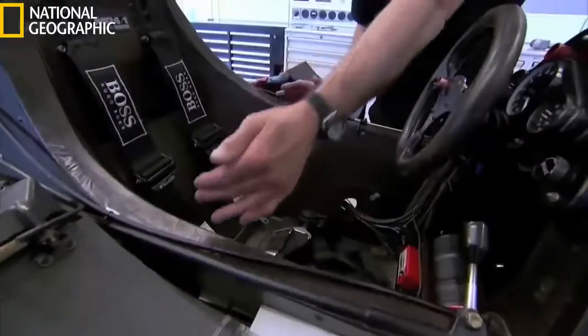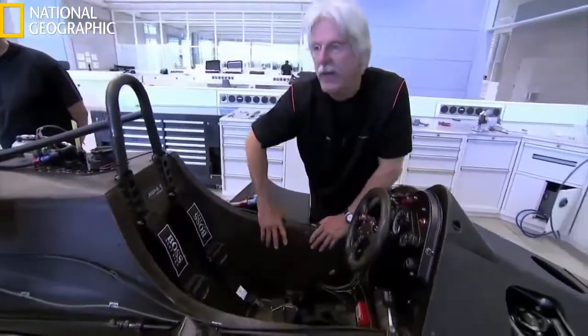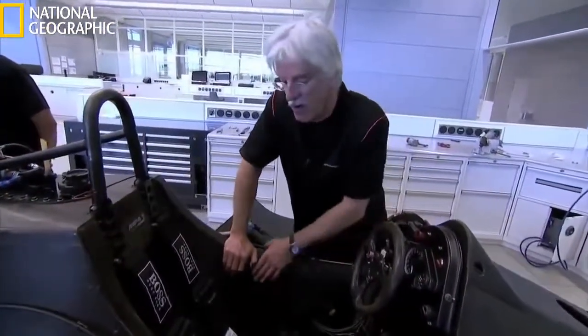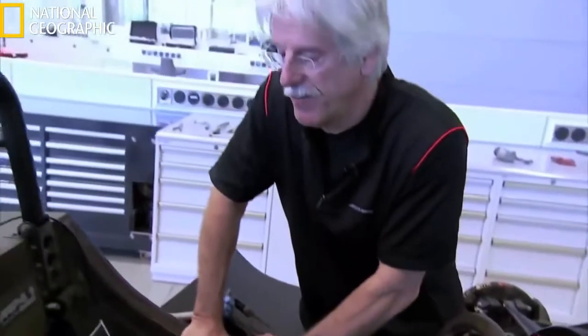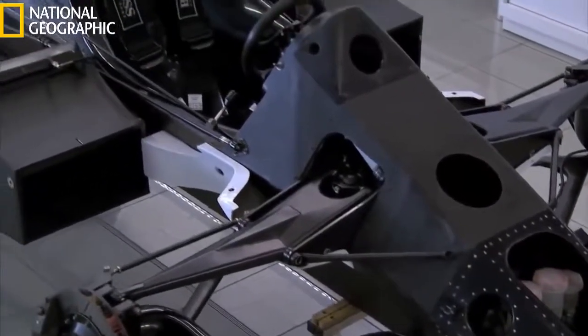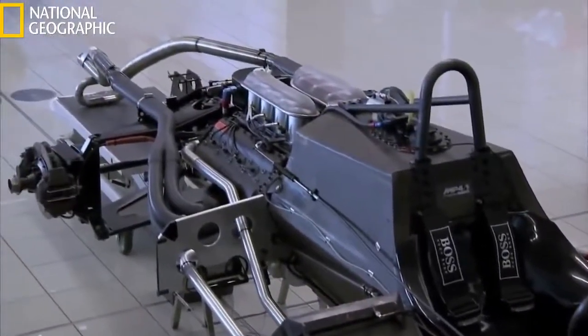Everyone had narrow chassis, same kind of shape as this. But because of this inherently weak area here, the aluminium chassis were twisting. When we did the carbon chassis, we realised we achieved 100% stiffer chassis than had been made before. So suddenly our car was, you know, the leading technology. Some of the other teams said that it was a fragile material, that it would shatter, but all the accidents we've had in it prove that it was up to the job. And since then, carbon chassis have got stronger and stronger and safer. But this was the start of it.